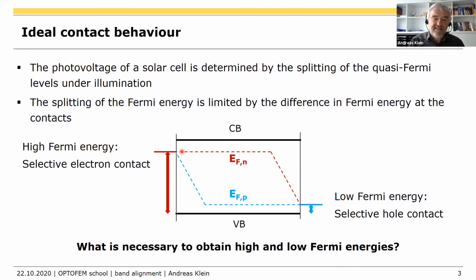Anyway, if we take this simplified picture, we say this is the splitting of the quasi-Fermi levels, the Fermi level of the electrons and the Fermi level of the holes. And the splitting of them gives us the photovoltage, and the splitting is limited by the difference of the Fermi energy at the contacts. So on this side, we have a Fermi energy which is high, that means far away from the valence band. This Fermi energy is low. It's close to the valence band.